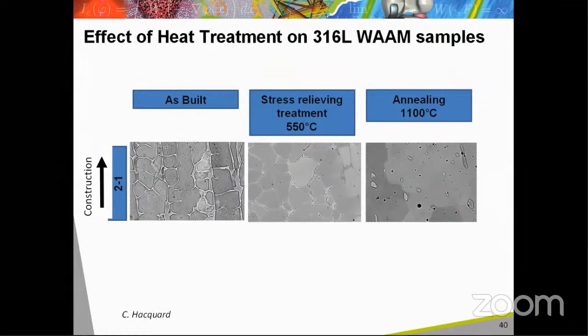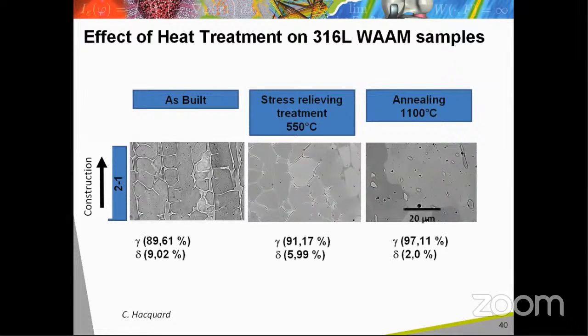These heat treatments change the material microstructure, and especially the content of the delta ferrite, as one can see on the micrograph. In order to observe the effect of the heat treatment on this detrimental phase, we have quantified the content of the delta ferrite in cross-sections using image analysis techniques. We observe the stress release heat treatment allows to decrease the content of the delta ferrite from about 9% to 6%. However, an annealing heat treatment allows to dissolve a larger part of the delta ferrite formed at the solidification.